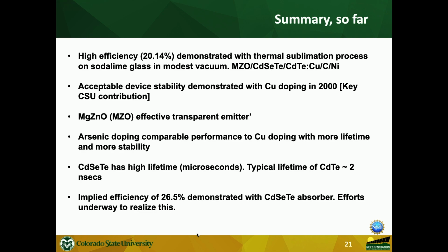We have demonstrated an implied efficiency of 26.5%. This was done with ASU and the National Renewable Energy Lab, demonstrated with a cadmium selenium telluride absorber, where the whole composition is just cadmium selenium telluride. It reduces the intensity of tellurium and has the potential to go further up, and this would put us on par with crystalline silicon. This effort is quite underway to realize this, and this is my summary of what we have done on cadmium telluride.